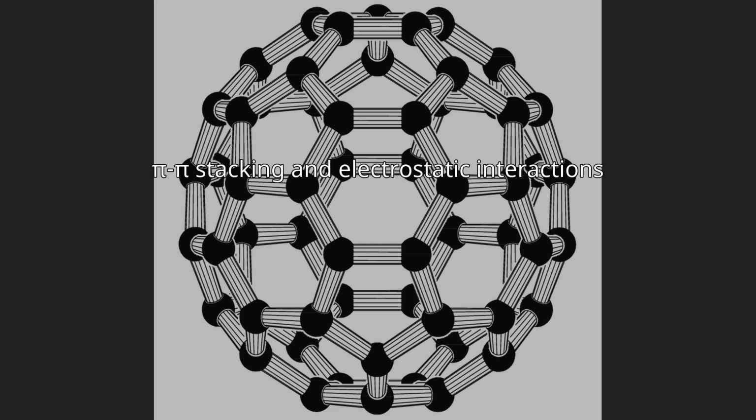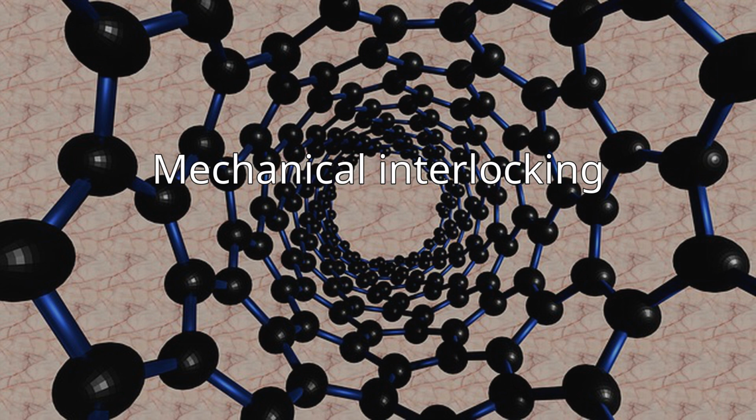Molecules that have bifunctionality are used to modify the carbon nanotube. One end of the molecule are polyaromatic compounds that interact with the carbon nanotube through pi-pi stacking. The other end of the same molecule has a functional group such as amino, carboxyl, or thiol. For example, pyrene derivatives and aryl thiols were used as the linkers for various metal nanobeads such as gold, silver, and platinum.